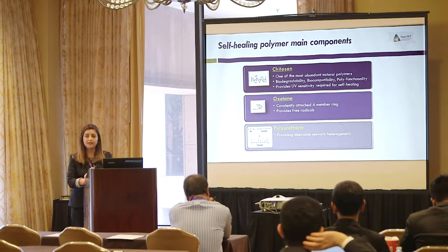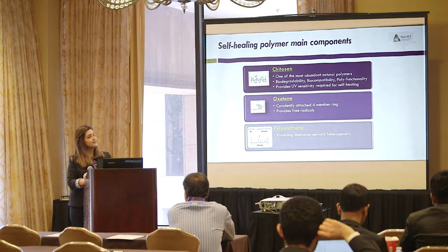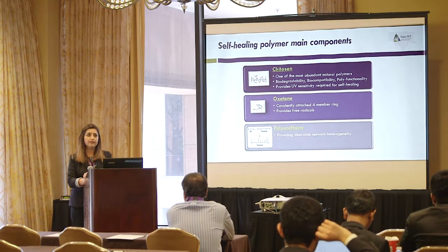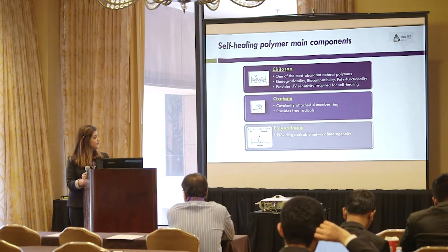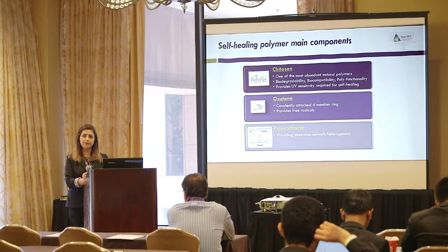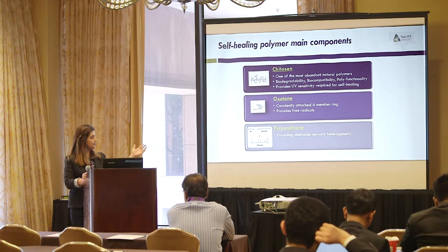Chitosan has UV light sensitivity. Oxetane has a ring structure, and when we break the structure of oxetane, it's going to produce free radicals. And the third component is polyurethane, which is the backbone of the self-healing polymer we're using. And oxetane-substituted chitosan is going to be mounted on polyurethane.